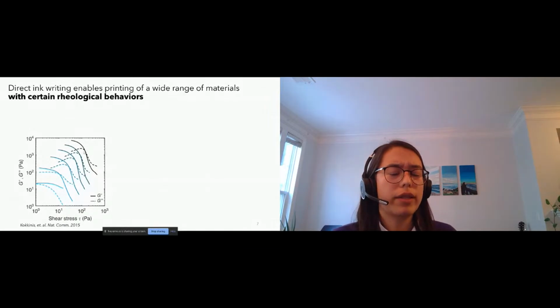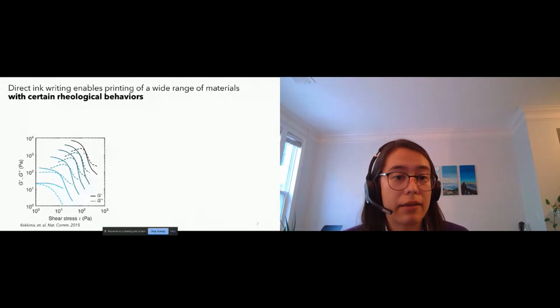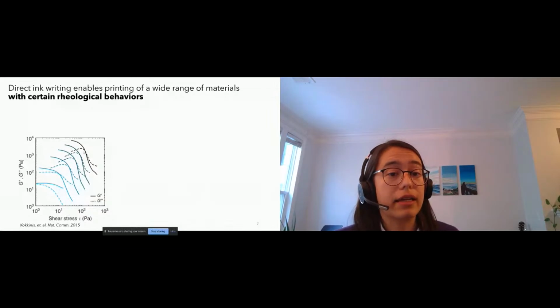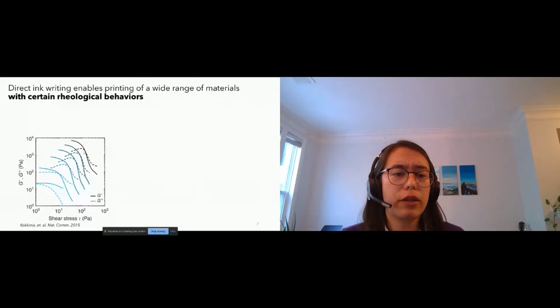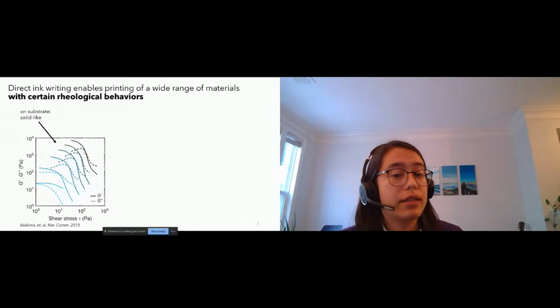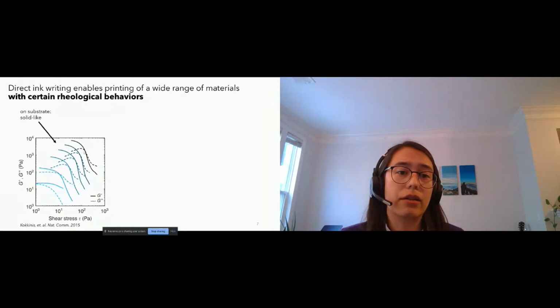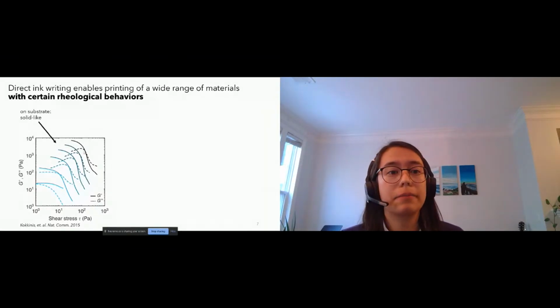What this means is if G prime is greater than G double prime, then that material is going to behave like a solid. And if G double prime is greater than G prime, that means that the material is going to behave like a liquid. If we look at low shear stresses, you can see that G prime is greater than G double prime. So it's going to behave like a solid there. And that's going to reflect the behavior of the material after it's printed onto the substrate.